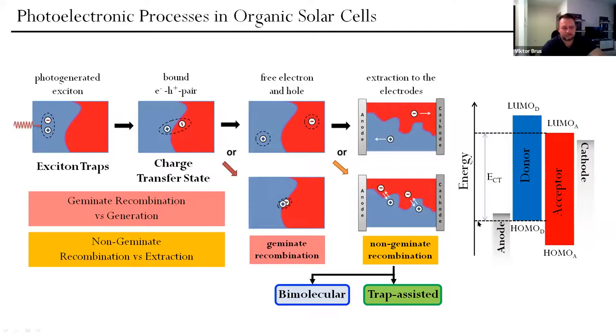And as I mentioned before, this effective band gap of the blend will limit the maximum open circuit voltage. If we make big gaps here, the effective band gap will be small and that means we fundamentally will not be able to achieve higher open circuit voltage. And since it is in the numerator of that equation, which defines performance of solar cells, we will fundamentally limit high performance for our system. So we always want to find some sweet spot by combining these two materials in the bulk heterojunction. Another thing which is important, which provides some limits for using different donor and acceptor pairs, is the morphology